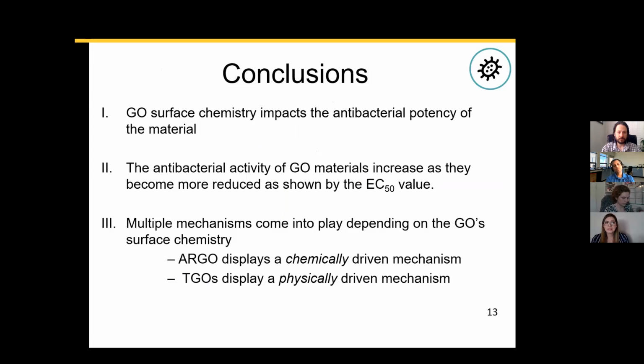Now, from this work, we can see that the graphene oxide surface chemistry has a really big impact on the antibacterial potency of these materials. We see that especially clearly when we calculate the EC50 values, and we see that the antibacterial activity increases as the materials become more reduced. We also see a shift in mechanism, where the more oxidized material displays a chemically driven mechanism, as shown by an increase in reactive oxygen species generation. But the thermally annealed materials display a physically driven mechanism, as we saw with the fluorescein diacetate dye, where there are perhaps more interactions with the membrane overall.